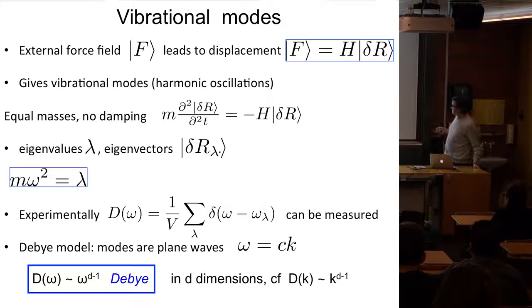In a crystal at low frequency, you would have plane waves, so you would have a linear relationship between frequency and wave vector. Counting the density of states is like counting wave vectors. As you remember from solid state physics, in d dimensions, the number of wave vectors k whose magnitude is k goes like the surface of a sphere, so it goes like k to the d minus 1. That leads us to the Debye result. For example, in 3 dimensions, if you have a crystal, the density of states grows quadratically.